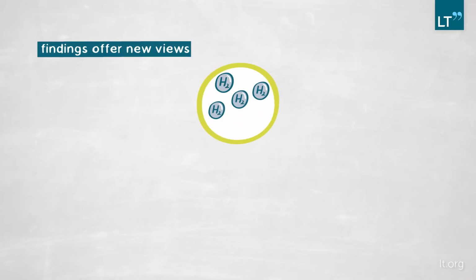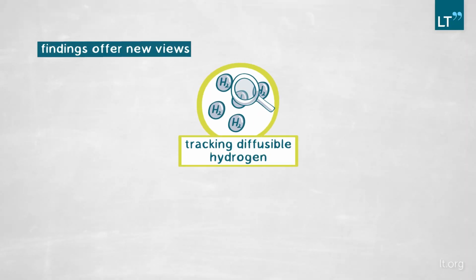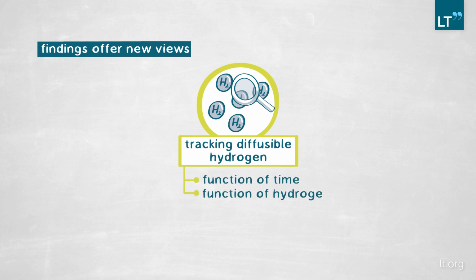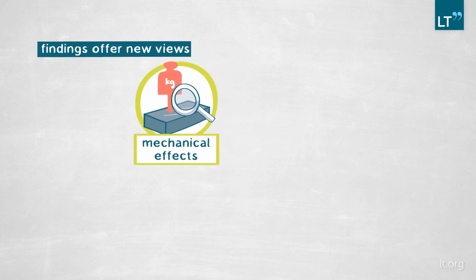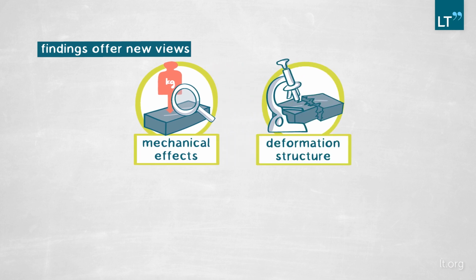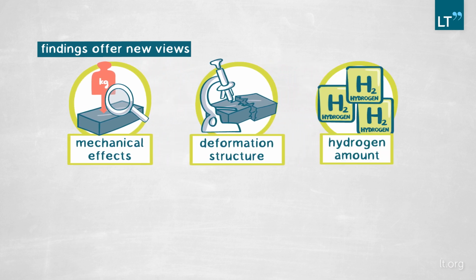The key relevance of our findings lies in the unique opportunity to test the mechanical behavior as a response not only to the trapped hydrogen, which is very well known in some cases, but also to diffusible hydrogen. Our findings show that we can track in a very reliable and reproducible way the effect of this diffusible hydrogen as a function of time and as a function of hydrogen content. If we now combine our findings on the mechanical effects together with the deformation structure, for example, by electron microscopy, and the amount of hydrogen that is located at the specific features, by collaborating with other groups in our institute, we can then have a holistic view of the material behavior, and we can also provide guidelines for simulations.